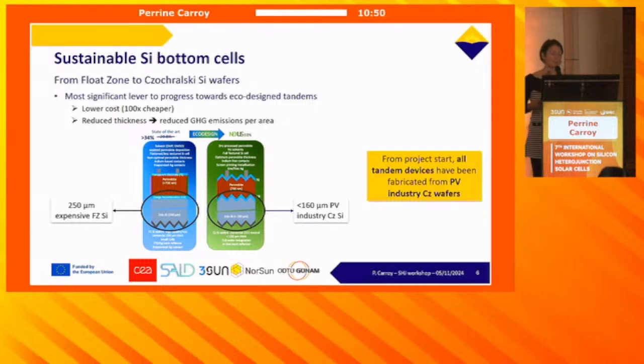So when you start from a silicon bottom cell that is based on this very thick, expensive float-zone silicon, the first thing you have to do to go sustainable is to replace it with Czochralski silicon that is typically used in the PV industry. Because, well, it's mandatory to be economically viable, and also by reducing the thickness, you automatically avoid a lot of CO2 emissions.